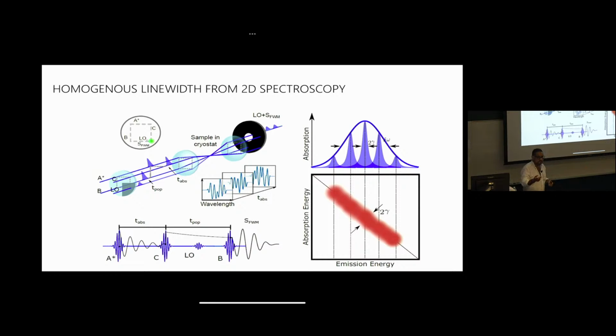But before that happens, before we dissipate this phase, we come in with another femtosecond pulse. Our first one set up this oscillation, and it all adds up, and it's a macroscopic polarization that is coherent, all in phase, well-defined phase. In comes the second pulse after some delay, but we haven't dissipated the coherence induced by the first pulse, and it drives the system further. It keeps driving these electrons further. But now you've got an angle between the two because you had one in A and one in B. There's an angle.